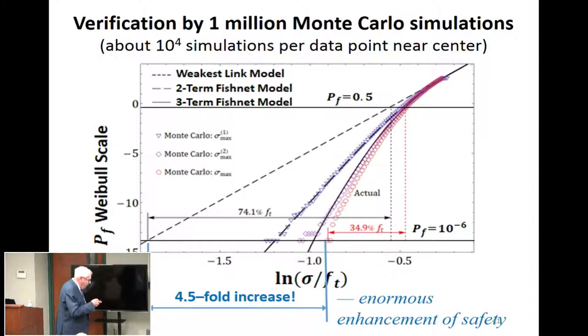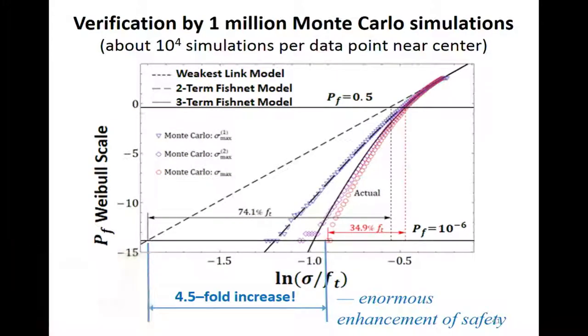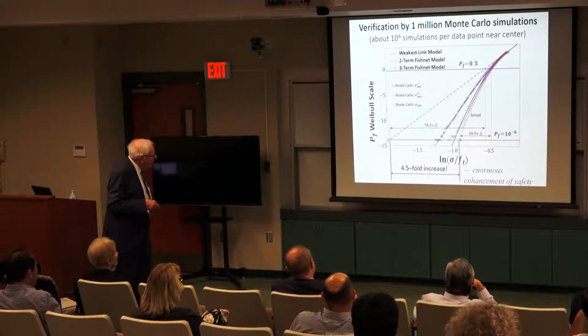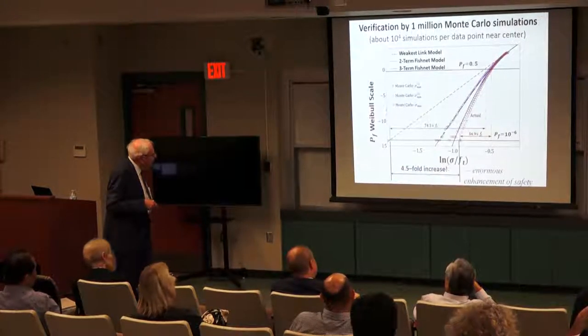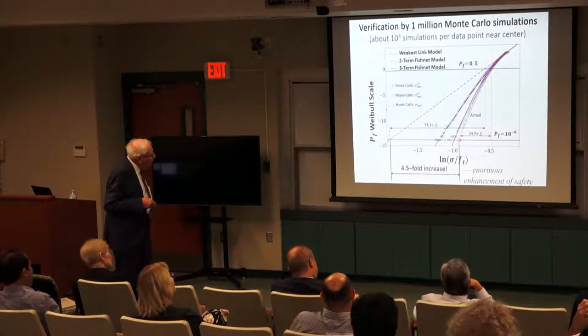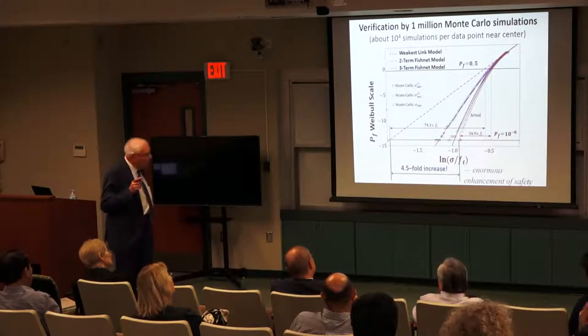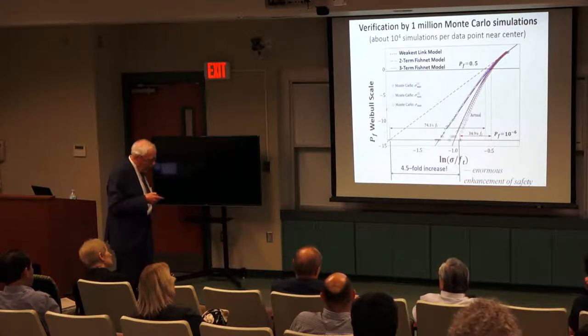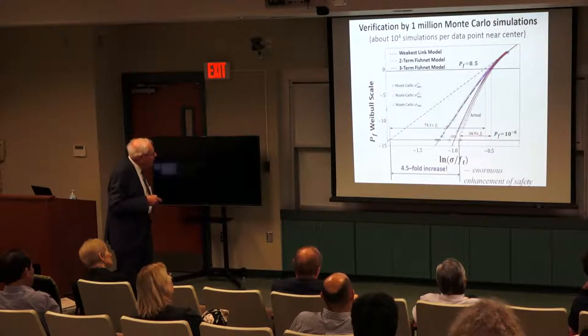Look at this result. So what Van Loo did, he simulated these fishnets in MATLAB. Such that for each case he ran 1 million simulations. I would have preferred 10 million at least, but it was good enough. This is the line of 10⁻⁶, and these diagrams are good up to about here, about 10⁻⁵. This is becoming too scattered. Now each of these points is an aggregate of 10,000 simulations, okay? So it's very smooth. It's virtually exact probability distribution.